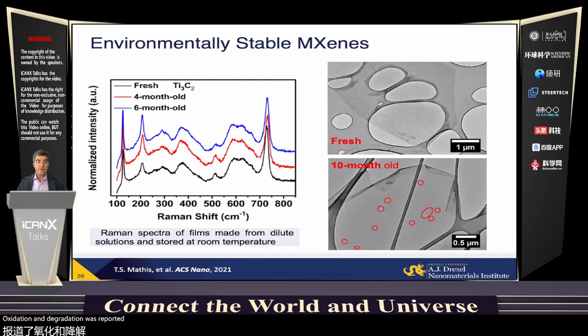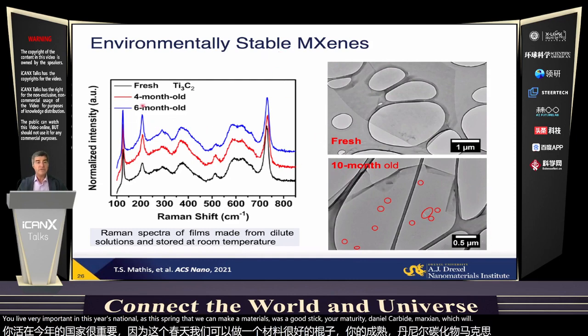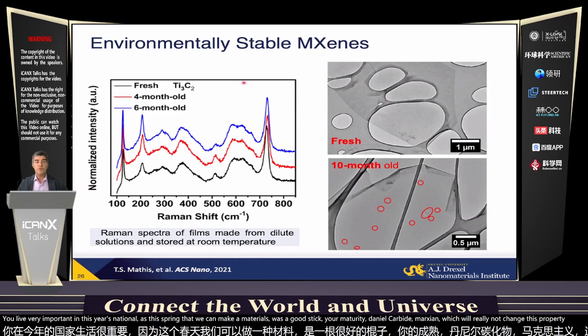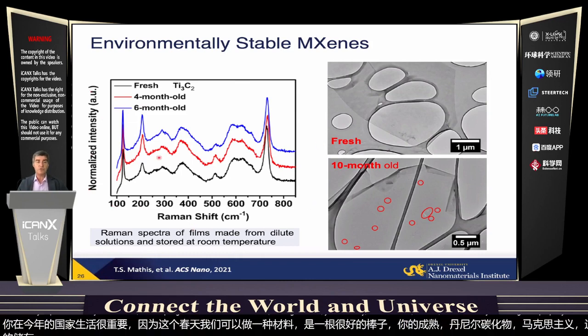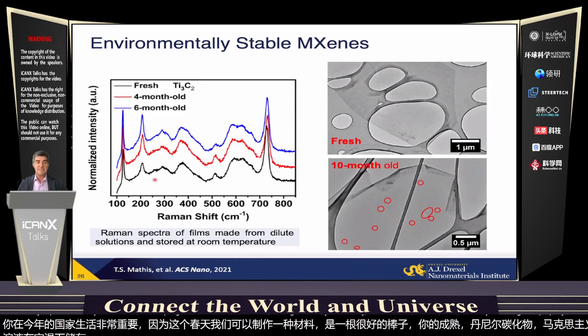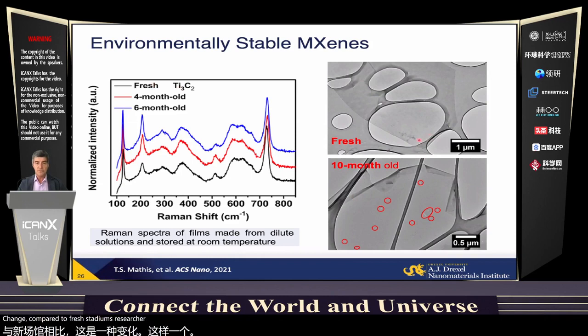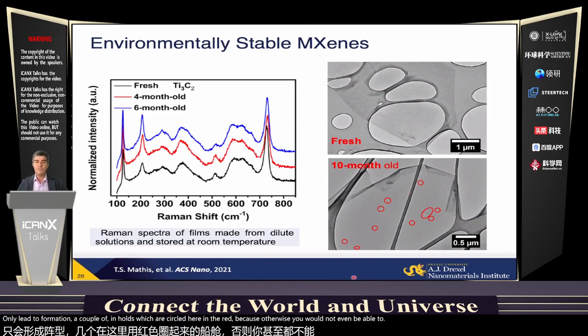Earlier, we reported in ACS Nano this spring that we can make materials with a good stoichiometry, titanium carbide MXene, which will really not change its property in dilute aqueous solution after storage at room temperature. For months, as you see in Raman spectra, which virtually don't change compared to fresh Ti3C2. And even 10 months of storage in solution only leads to the formation of a couple of pinholes, which are circled here in red, because otherwise you would not even be able to find them.